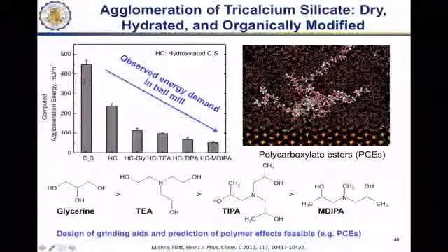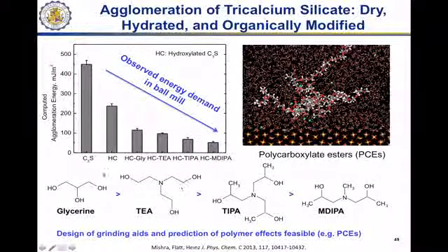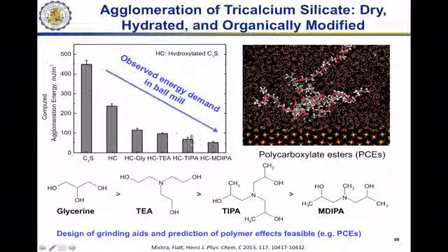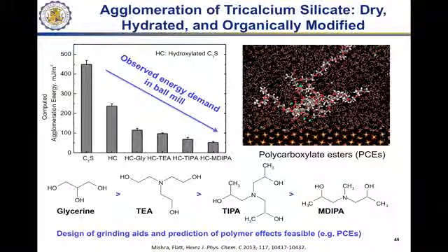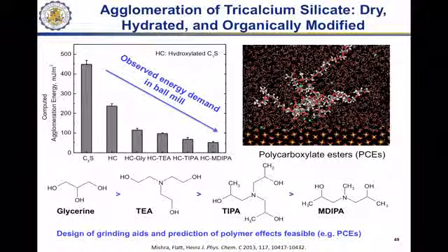And so through these models we developed, that meet all those interface standards of structural reproduction and reasonable cleavage energies, we're actually able to explain the mechanism of grinding aids that are used in cement plants for cement grinding, even able to make some predictions of how we should design new molecules to increase the energy savings in those applications. And then also we're looking at hydrated surfaces. We have models for tobermorites and so on included that can describe the interaction with polymers and aqueous solutions, hydration reactions of cement.